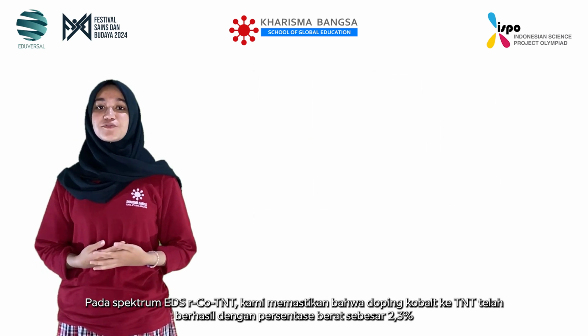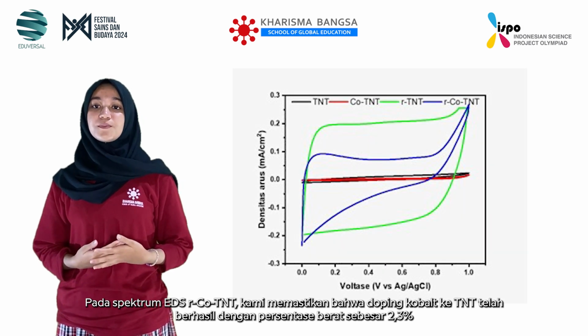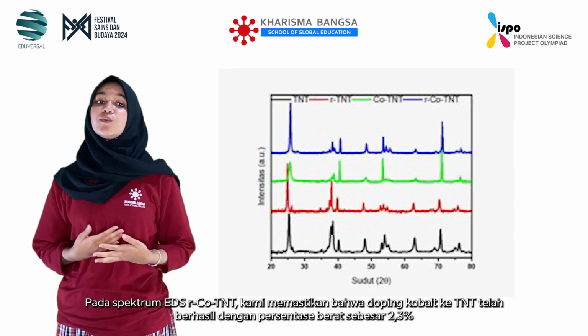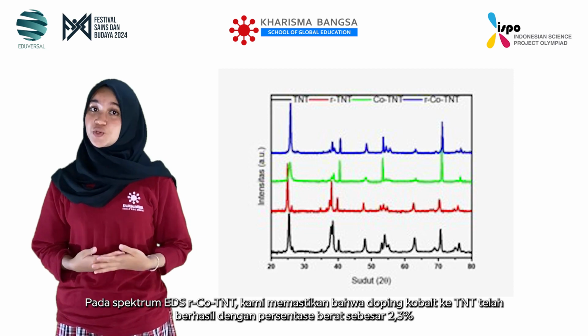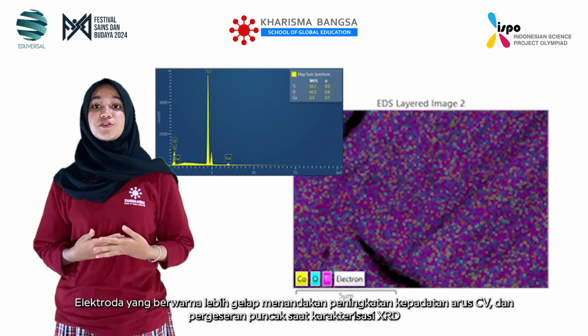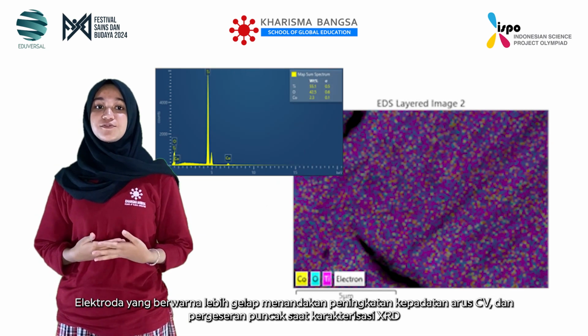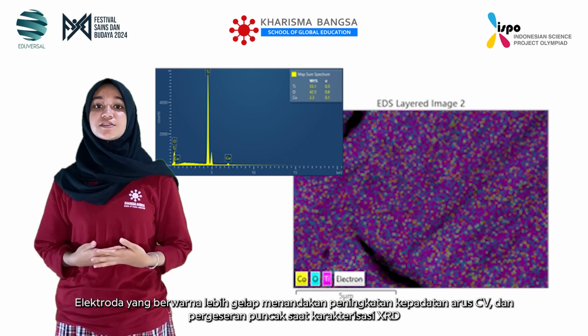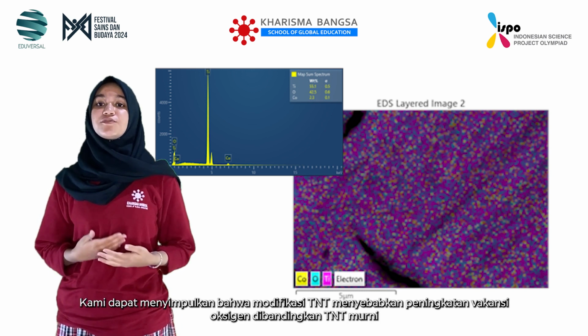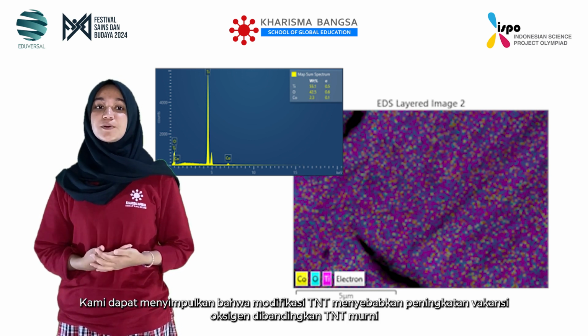From EDS spectrum of RCo-TNT sample, we confirmed that the cobalt insertion to TNT was successful with the weight percentage of 2.3%. From the darker color of oxide, increased current density of CV, and peak shifting in XRD characterization, we can conclude that the modification gave rise to the oxygen vacancy population compared to pristine TNT.